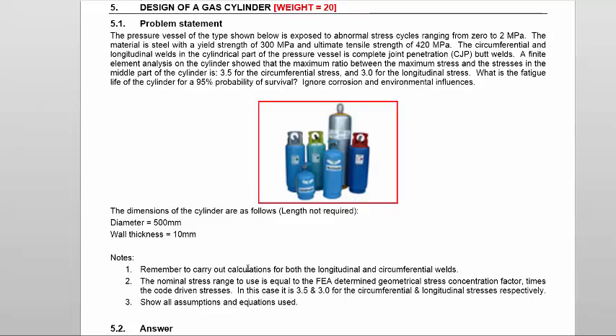This is a straightforward problem. Calculate thin wall stresses multiplied by 3.5 and 3.0 for the respective directions. Remember the crack can initiate in the throat of the weld and at the toe — look at the applicable SN curves and explain where the weakest point is. Present your results. I hope this helped.